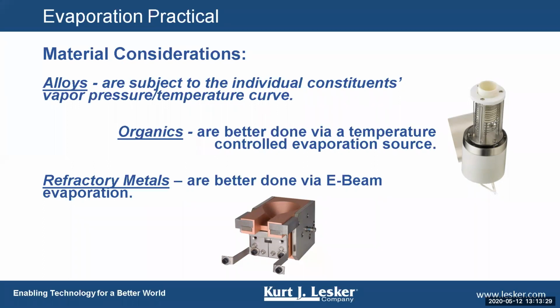Question about thermal conductivity between crucible liner and the hearth. Is it in general a good or bad idea to use a spacer between the liner and the pocket? Yeah, as I pointed out in E-beam, if you understand the thermal conductivity path through the gun, you can do things like add a spacer. What does the spacer do? It acts as a thermal break in essence. It's another thermal interface, so it slows down the thermal conductivity through the material and keeps more of the heat from the E-beam in the material itself. So for a given rate, you can run at a lower power now.